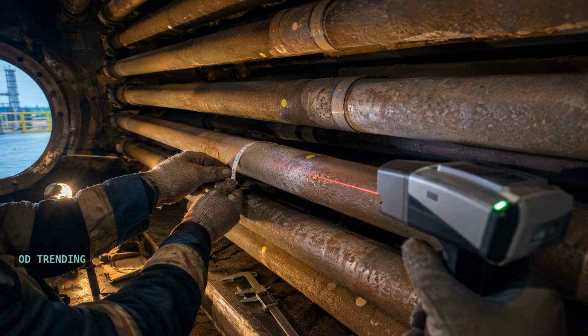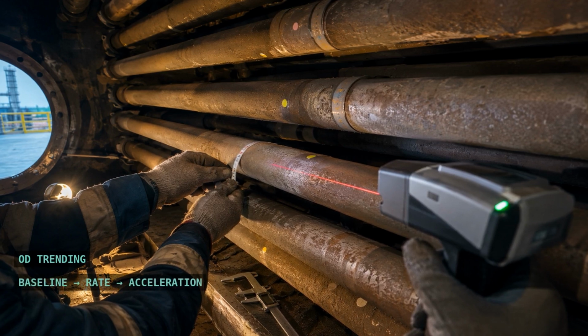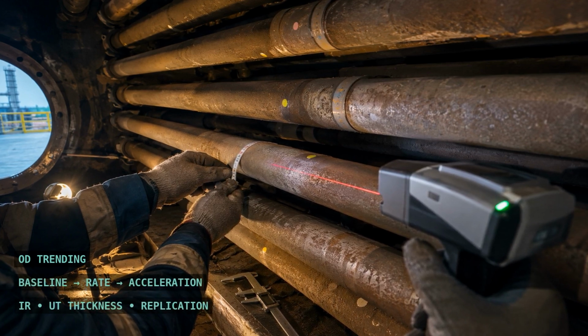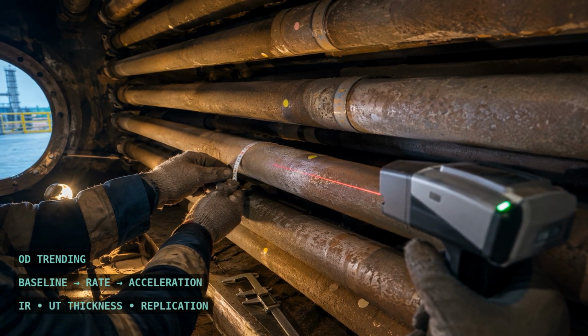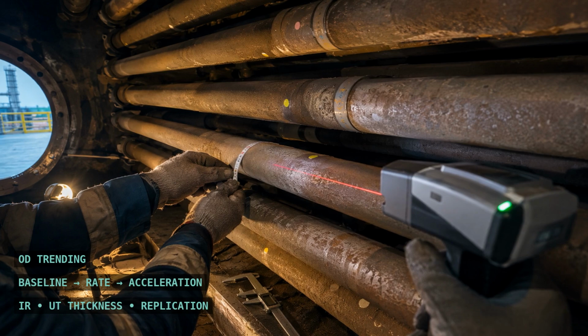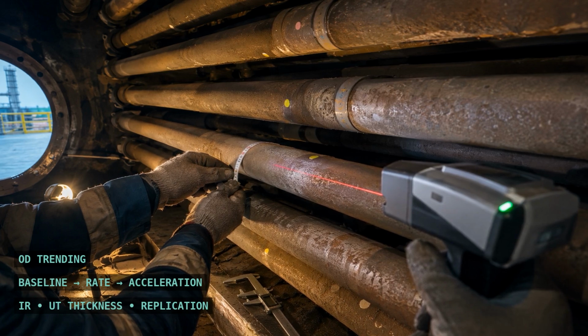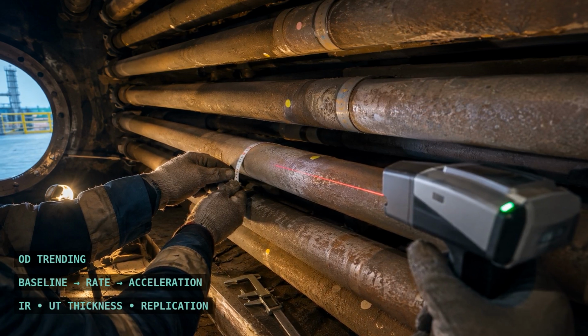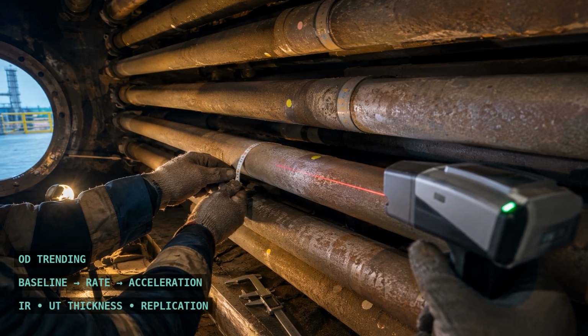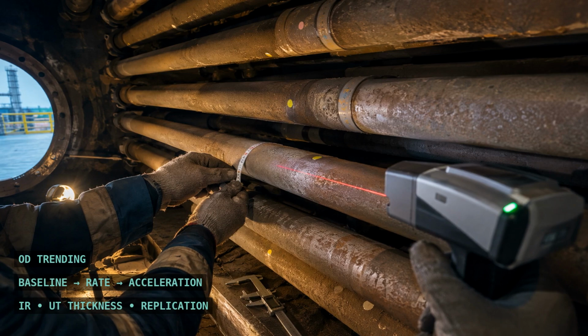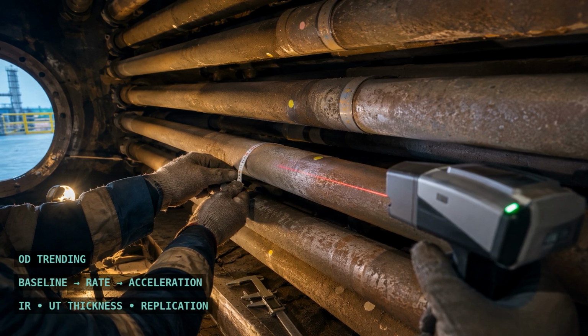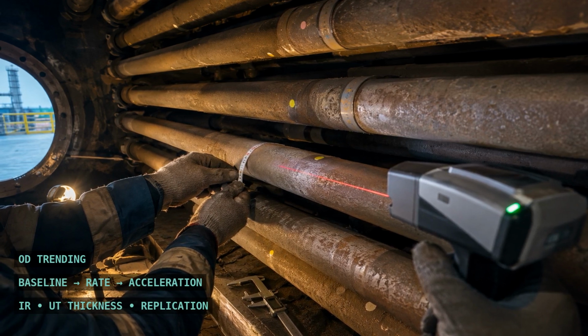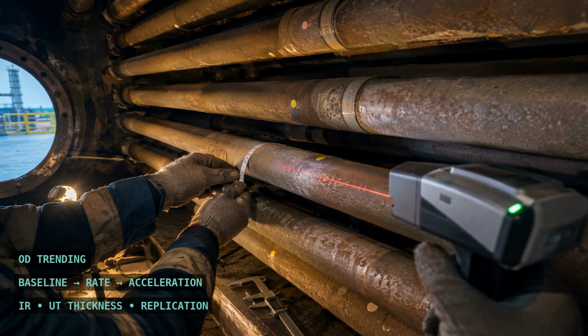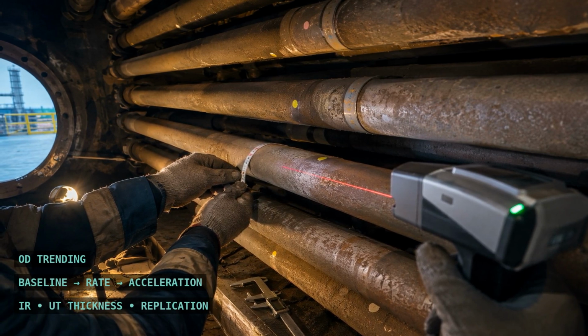The good news, this failure announces itself in advance in millimeters. On the outside of the tube. If you're looking. Inspection teams measure tube outside diameter at fixed, marked stations along each tube with calipers, with pi tape that converts circumference to diameter, or with laser profilometry that maps the entire surface. They map each bulge along the length and around the circumference, comparing tube to tube to find the hot lane.